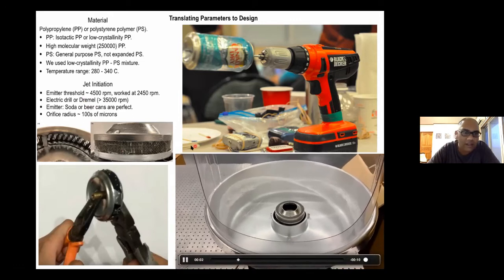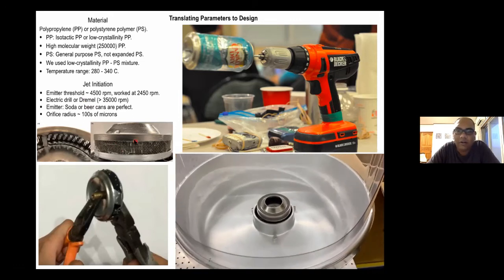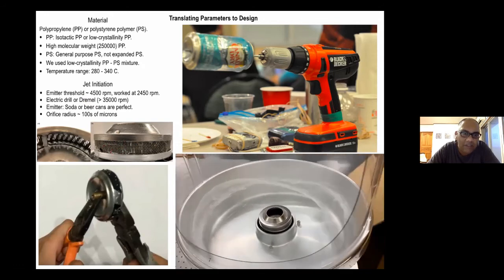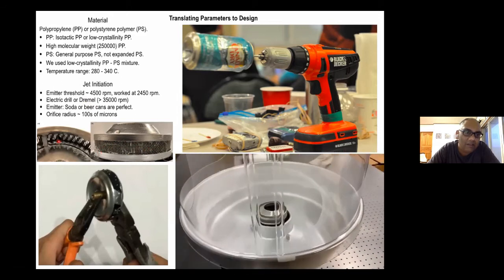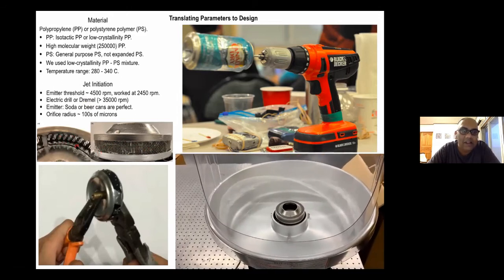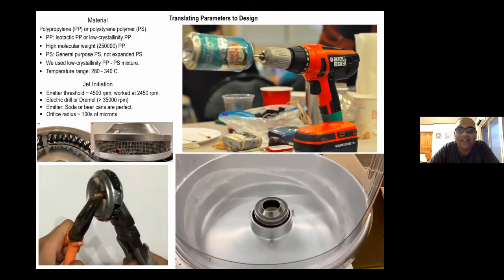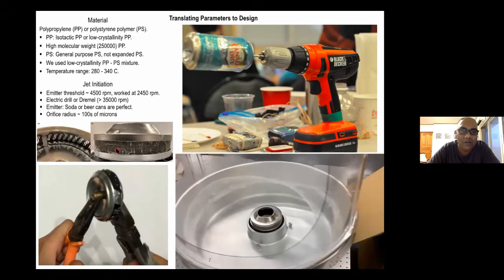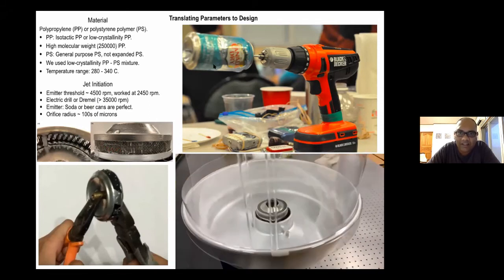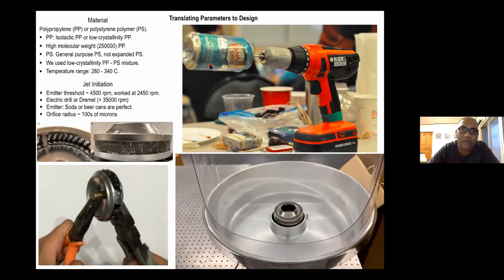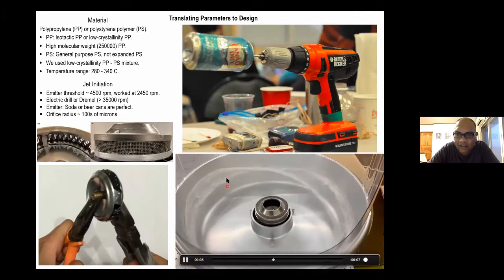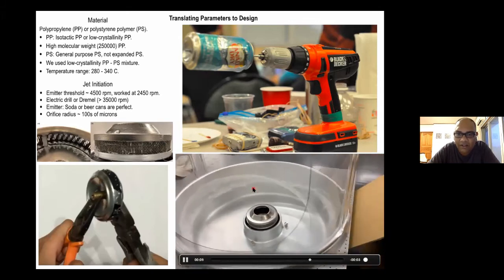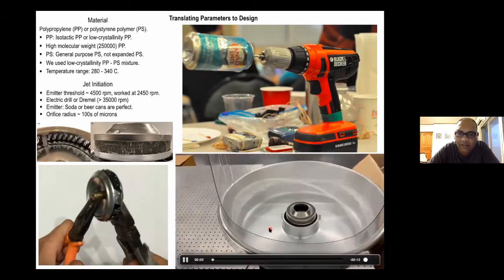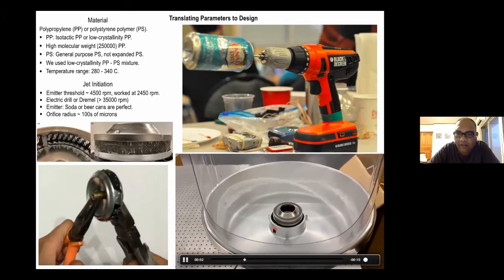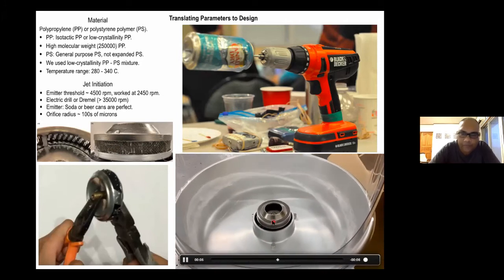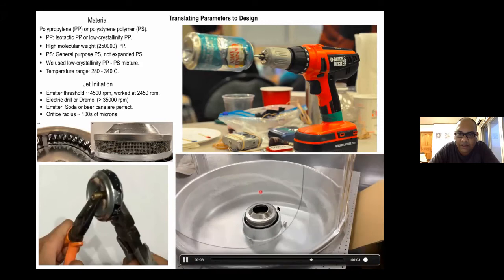Another thing I want to point out is, if you are working with a commercial cotton candy machine, they usually come with a mesh of the order of millimeters, or with vertical or diagonal slats. Then you tend to not get as good a fiber diameter. So I replaced this mesh with the aluminum can with holes drilled to the lower diameters that I wanted. This was from one of the early videos. You can see this was a commercial cotton candy machine. The first one died, unfortunately, but by then we were able to get delivery of this, and I changed the emitter, and this is the fabric that we were generating for polypropylene.